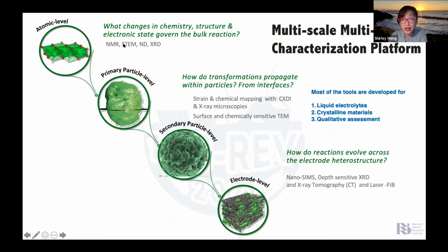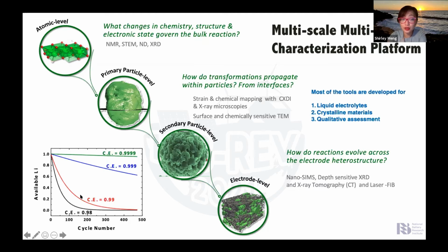So when we think about battery research in my group, we spend a lot of time using advanced characterization techniques like X-ray, neutron, and NMR-based techniques to understand every level of a battery, all the way from atom level to particle level to electrode level: where the degradation mechanisms happen, and what kind of interface forms. We have to do that because at every part of this scale, if something happens that causes inefficiency, a battery with only 99% Coulombic efficiency will quickly degrade after 300 cycles. But for a good battery, you need very, very high Coulombic efficiencies, preferably three nines. This imposes very significant challenges for scientists who work in the battery field.